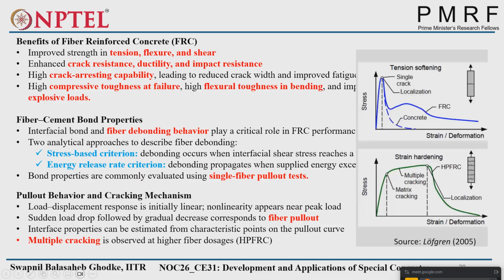Interface property is also important. And if you have a higher amount of fibers, what happens? The first crack will appear here. After that cracking, multiple minor cracks will happen. This is the multiple cracking region. That multiple cracking region will give minor cracks, but will not allow the specimen to fail. And after some time, after multiple cracking, fiber pull-out will start here, and each fiber will get pulled out, and then the specimen will fail here. So this fiber reinforced concrete allows more life, basically more resistance to the load compared to normal concrete.